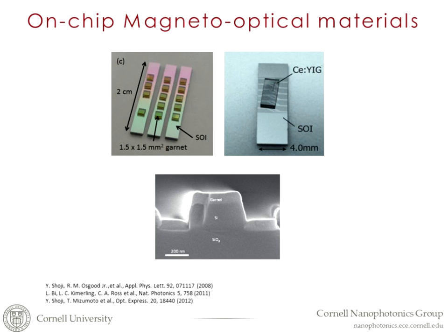However, integrating these magneto-optical materials on chip is fundamentally challenging. For example, you can do wire bonding, you can do wafer bonding or chip bonding, like the first two figures on top. And the bottom figure is monolithically integrated, basically directly depositing these MO materials on the silicon wafer. But for these kinds of approaches, these magneto-optical materials usually have much lower quality than single crystals, which is very apparent. And in general, these magneto-optical effects in the optical domain are generally weak.